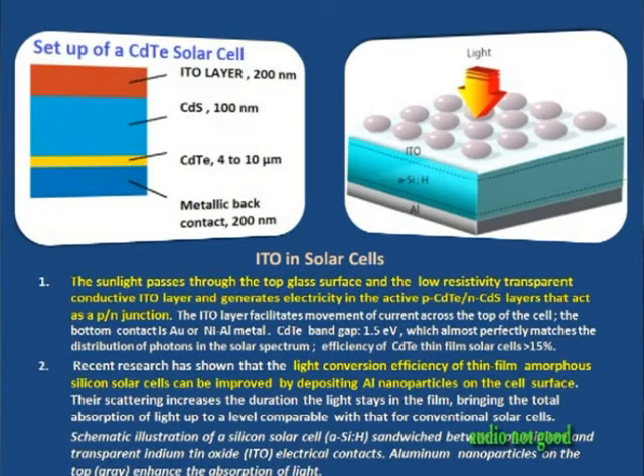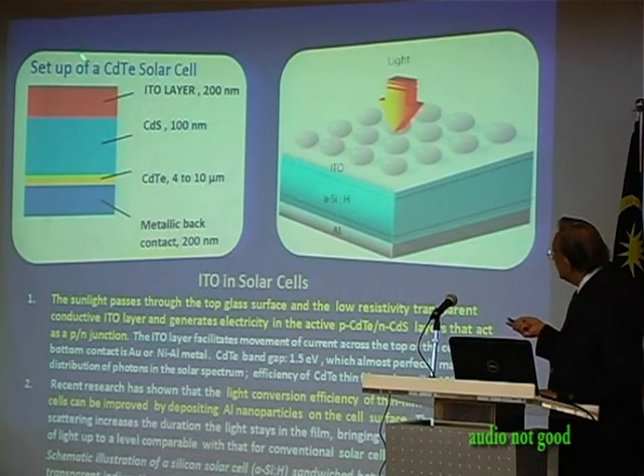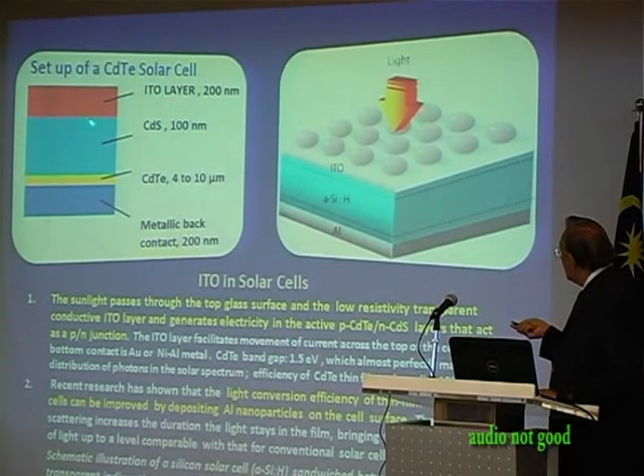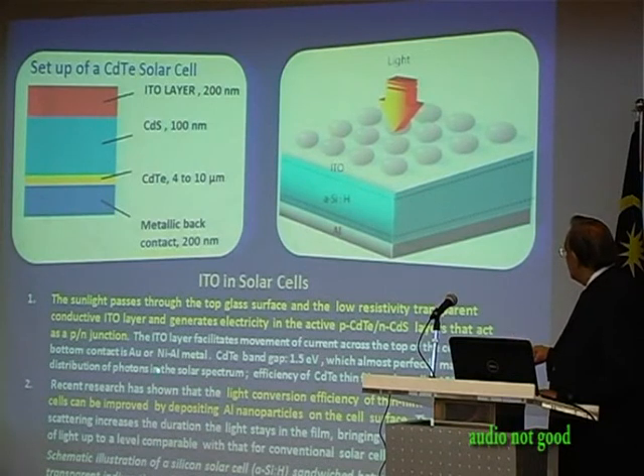In the area of solar cells, I've given two examples here. Cadmium telluride solar cell: the light comes straight through the top glass surface, through this low resistivity transparent indium tin oxide layer onto the PN junction here. The cadmium telluride is the P and then this is the N. So electricity is generated. The ITO layer facilitates movement of current across the top of the cell, and you have a metallic back, which is normally gold or some aluminum alloy.